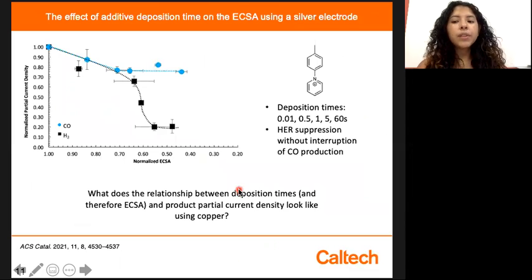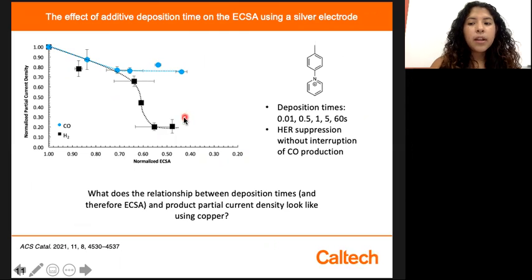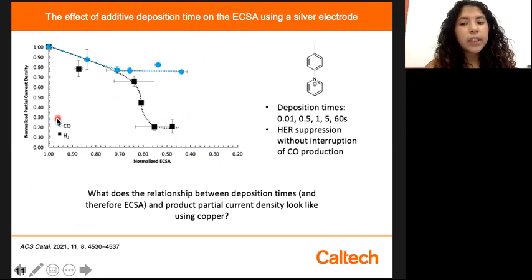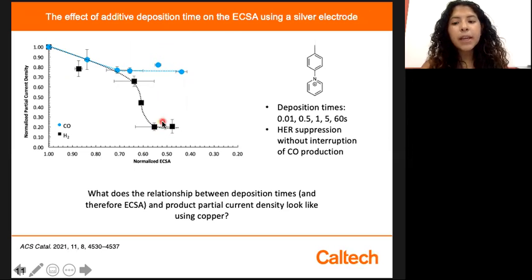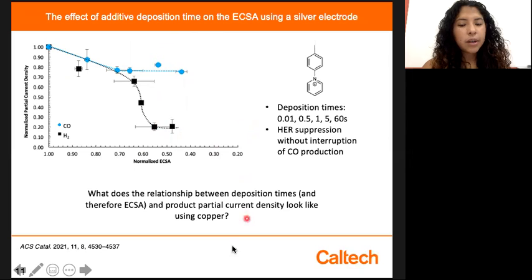And from the results using small scale deposition times, they were able to see that when they plotted the partial current density normalized to the ECSA, after a certain point the deposition no longer had an effect on CO formation, but instead had a dramatic suppression of HER. And this became the basis of my project because we wanted to see how these results translate to copper electrodes.